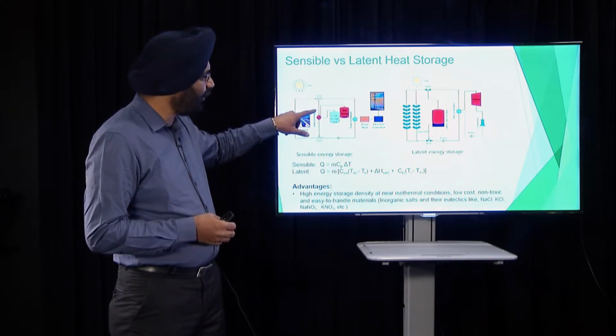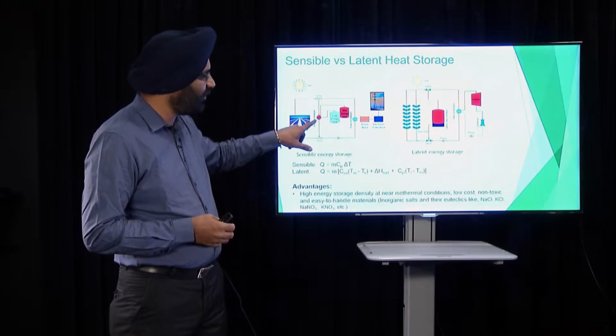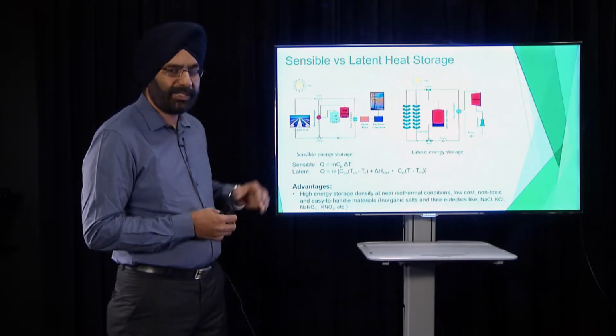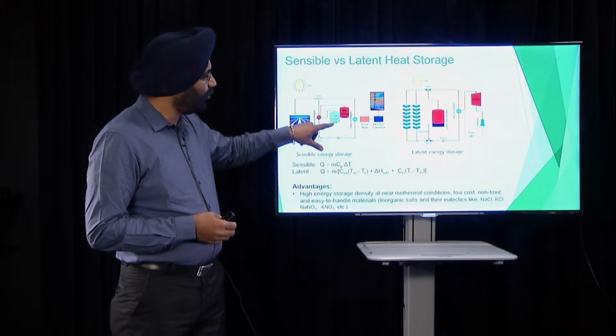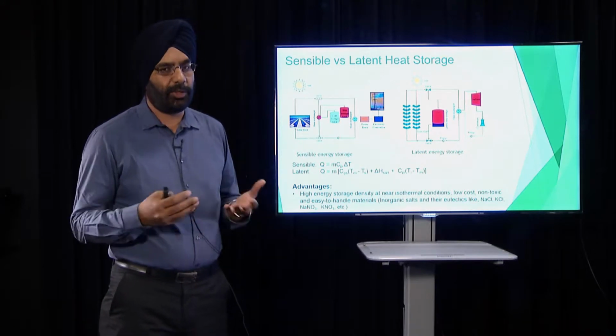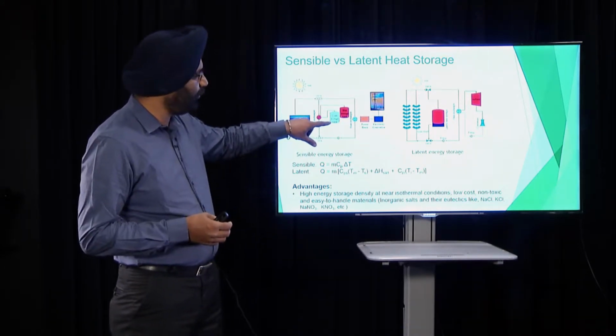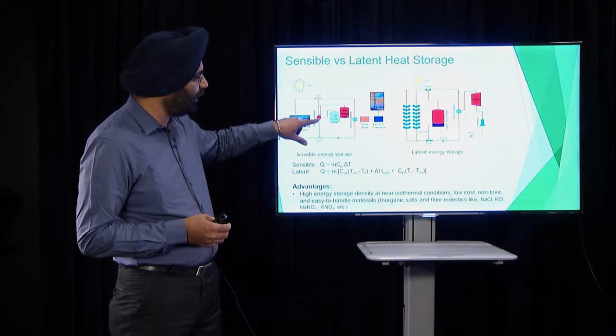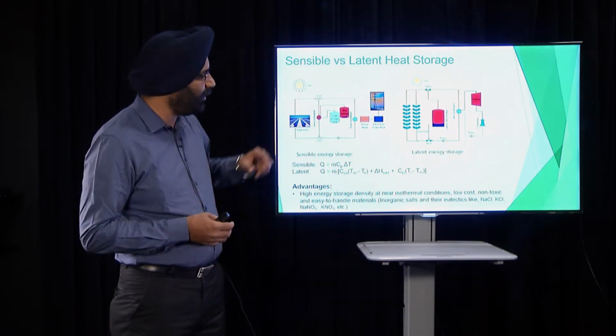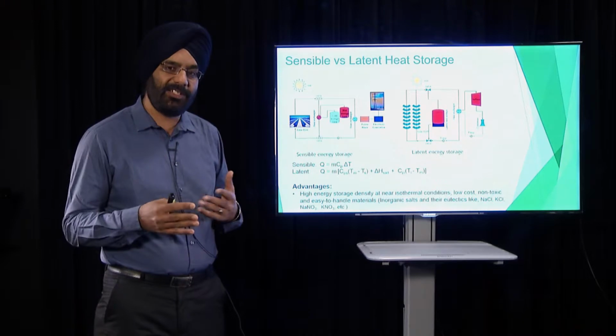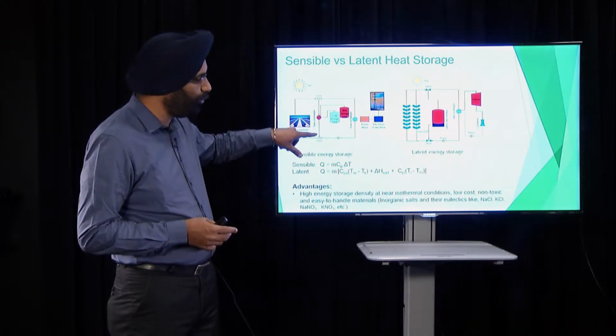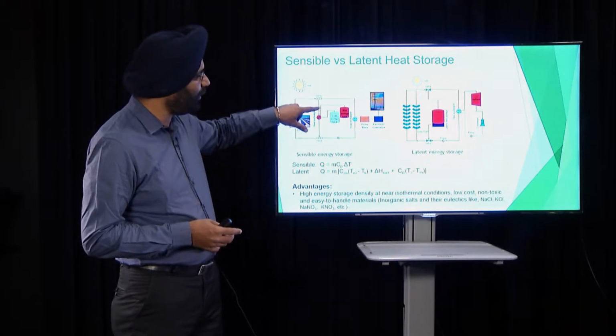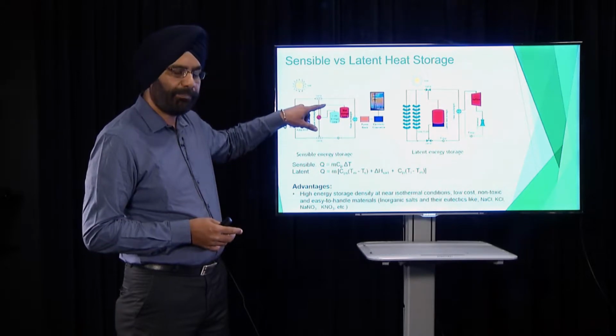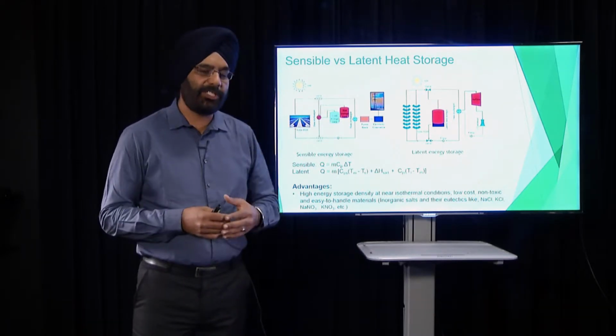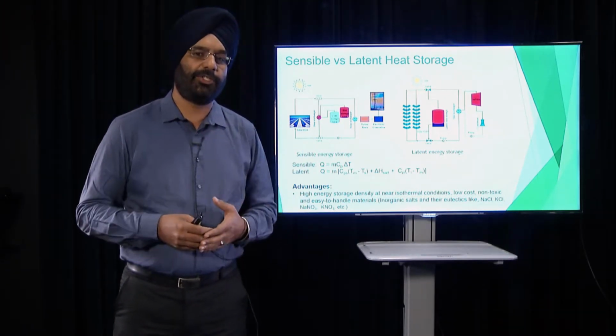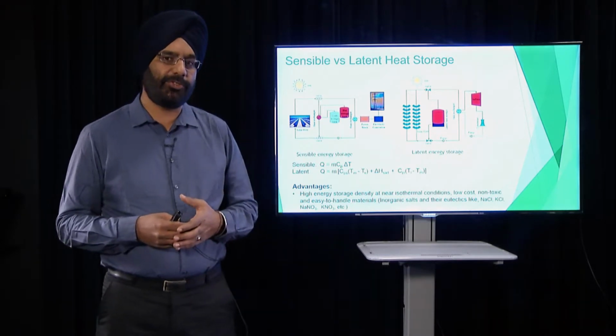But a part of the heat transfer fluid goes through a heat exchanger. Now what happens at the heat exchanger is that the storage material, which is a molten salt, salt in a molten state, is pumped and comes to the heat exchanger, where the heat transfer fluid and the storage material exchange their heat. As a result, the heat transfer fluid cools down, whereas the molten salt heats up. So you can see there is a red in there, and that heated molten salt goes to another tank, which is called the hot storage tank. And this technology is called the two-tank molten salt storage technology.